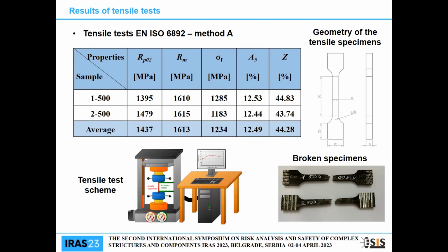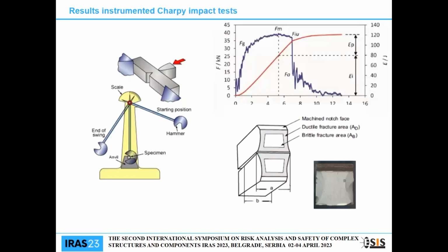We can see that we are inside what the producer promised. The yield point was above 1,400, and the ultimate tensile strength is about 1,600. But with this charge, we get good elongation, which is maybe 40% of what we promised, and the contraction was also quite good. This is due to the last heat treatment of this steel.